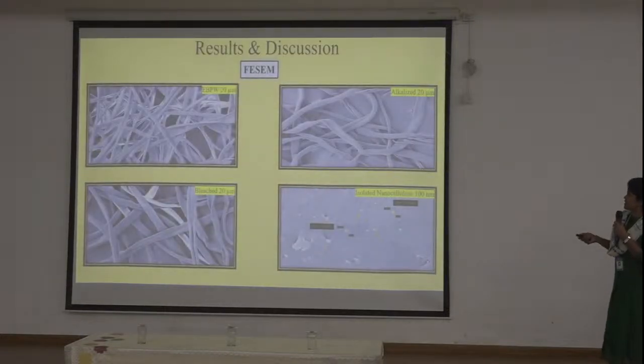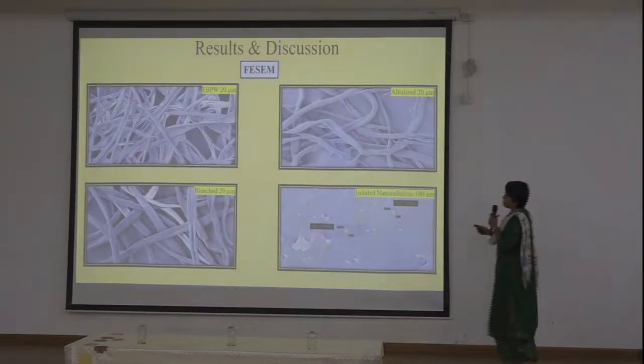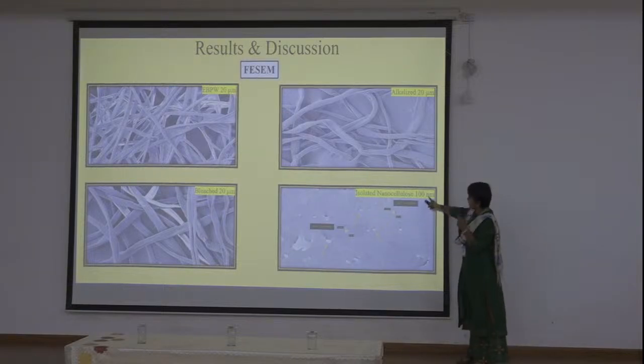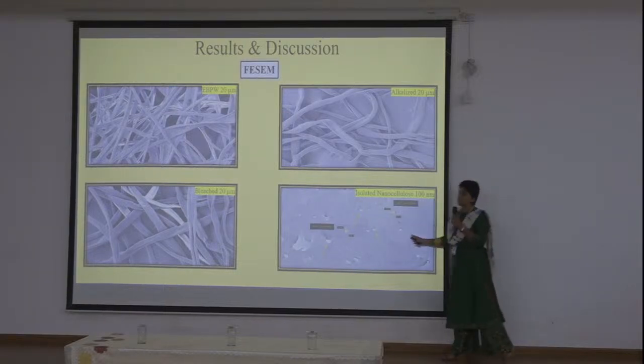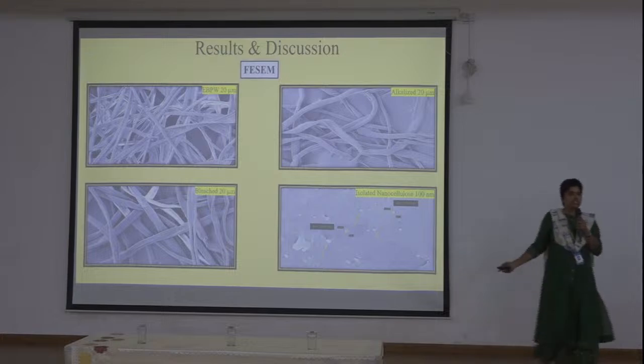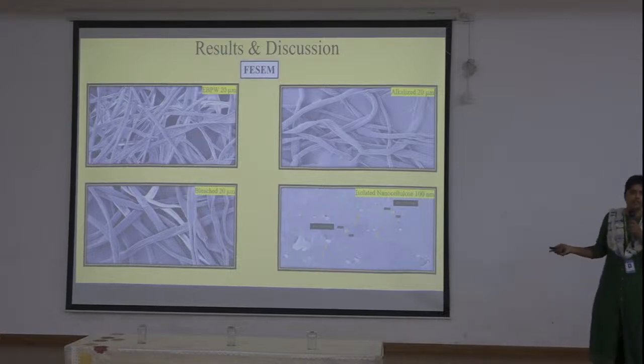This is the image of SEM. In SEM, images of all 4 samples were taken and the isolated nanocellulose confirmed the presence of spear-shaped nanocellulose with an average diameter of 30 nanometers.